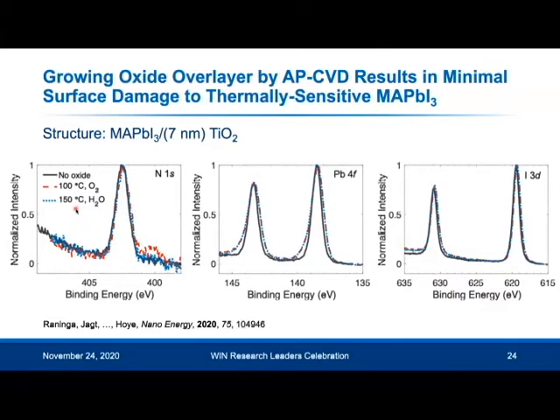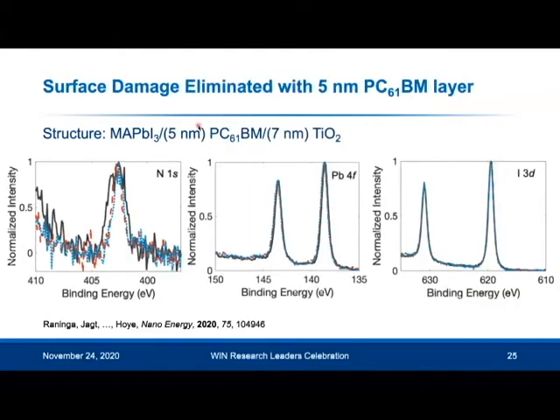And we next wanted to see what happens if we have a very thin layer of our electron transport layer, because in our full devices, we need to use 40 nanometers of PCBM to form a good interface for electron extraction from the perovskite. Now, of course, with XPS, we can't see through 40 nanometers of PCBM, and we can't really mill through it either. It's not really amenable to milling.